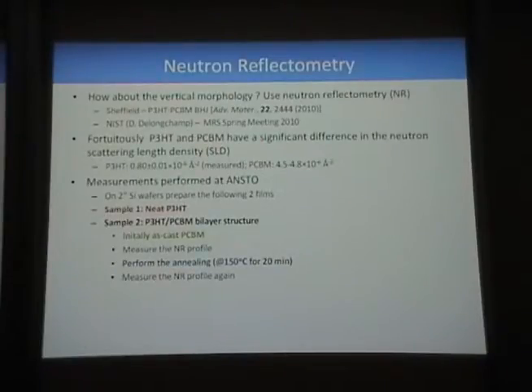Now, luckily for us, P3HT and PCBM have a significant difference in the neutron scattering length density. For P3HT, it's been measured to be 0.8, while for PCBM, it's between 4.5 and 4.8. So it's quite good. These measurements were performed at ANSTO, down in Sydney. That's where the only nuclear reactor is in Australia. And this was done on 2-inch silicon wafers, and we prepared the following 2 films. Sample 1 was just a film of neat P3HT, so that we could measure the scattering length density for the P3HT. And sample 2 was the bilayer structure.